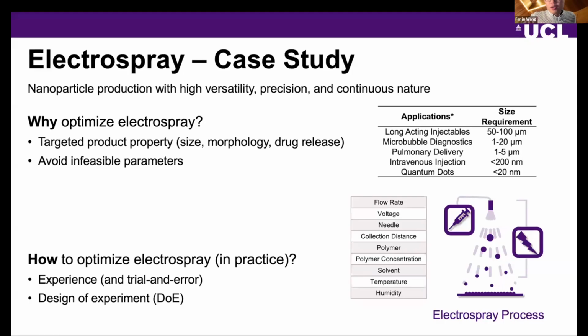When you press it, then the liquid will be drawn out and will form very, very tiny little droplets. And fortunately, here we're using some volatile solvents so that the solvent will evaporate and leave all the residues, which turn out to be tiny, tiny particles. And electrospray is just an advanced version of the spray drying and makes much, much finer particles and gives us a broad range of particles we can make by changing its processing parameters, as you can see from here.